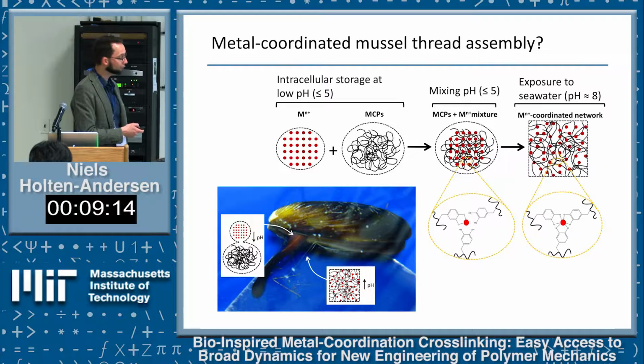What the mussel then probably takes advantage of is that once this initially fluid secretion gets exposed to seawater—once the tissue pulls back and exposes the fluid filament to seawater—there's a big pH jump. Seawater is typically around pH 8 to 8.1, depending on where you are in the ocean. Once that happens, once the pH jumps up, the organic ligands that bind the metal ions become much more strongly binding. They deprotonate—these hydroxyl groups become an O minus that really wants to donate its electrons to the metal's d orbitals. Long story short, this pH switch drives the formation of the crosslink and solidifies the material really, really quickly.